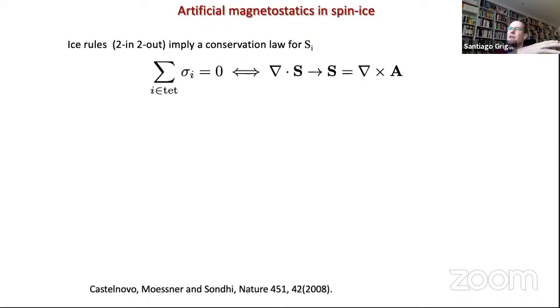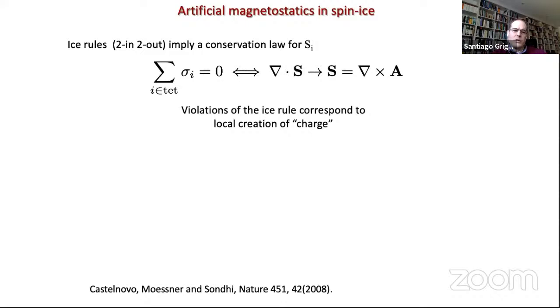And you can see it in the sense that in Onsager's argument, this idea that you were threading a string through all these corners was already talking of some sort of conservation. And as you see, essentially the ice rules are telling you that because you have 2 in and 2 out, the sum over those 4 on each tetrahedron should give you 0. So that's telling you of some sort of a conservation law. And if you go from this discrete version to a continuum version, that conservation is expressed in terms of divergence-free fields. And of course, once you have that, you can think that you can write that as the curl of some vector potential.